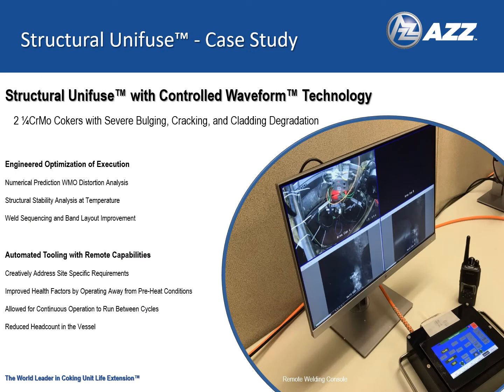Here's a case study that exemplifies some of our capabilities. AZZ was contracted to address shell bulging issues in two 29-foot diameter coke drums in central Canada. Wall thickness in the areas of concern were 1.5 and 1.88 inches. Base material was SA-387 Grade 22 Class 2 with SA-240 410 stainless steel cladding. Although this configuration of repair and vessel are fairly common, the project had some unusual requirements.